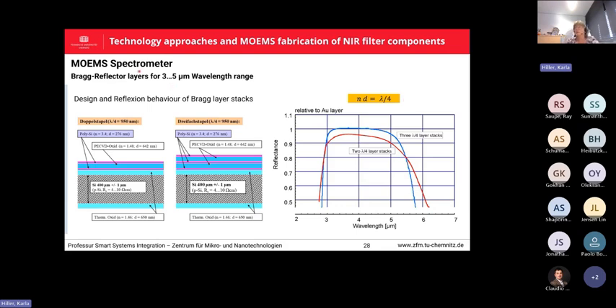So for this 3 to 5 micrometer wavelength range, we have chosen a thermal oxide, a polysilicon, a PECVD oxide, and again a polysilicon as a double layer stack compared to a triple layer stack with the same materials. And the anti-reflection coating in this simple case is just an oxide with a quarter wavelength stack. And this is the reflectance compared to the gold layer. That's why it ends up with 100% here.